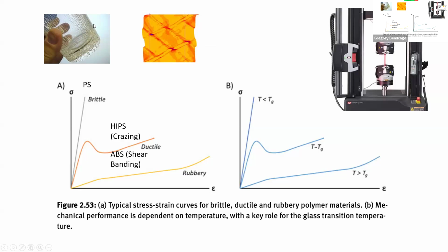So there's no volume change in it, but what it is, they're little micron-sized cracks, smaller than a human hair, that are bridged by polystyrene fibers. So it makes like a hairy thing. The fibers kind of reinforce it, but eventually the fibers in the middle break, then a larger crack grows, because the Griffith criterion is that the smaller the crack tip size, the more stress you have, so it breaks faster. So basically these are micron-sized crack tips all throughout the material, so it just crushes down to nothing. Right, so crazes are bad.